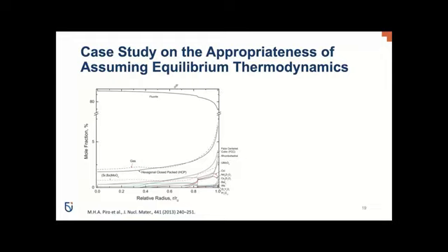Now, what's noteworthy here is that we see this fuel that's been irradiated. The models were directly compared to post-irradiation examination experiments that were conducted at the Joint Research Center in Karlsruhe, Germany. And what's noteworthy is that both in those specific experiments and consistent trends that have been observed in UO2 fuel, you generally only see 3 phases, with some exceptions of a few others. You really only see your fluorite, you see your gas, and you see the noble metal hexagonal close-packed phase. Sometimes you might see some evidence of perovskites and perhaps something else, but that's kind of rare.